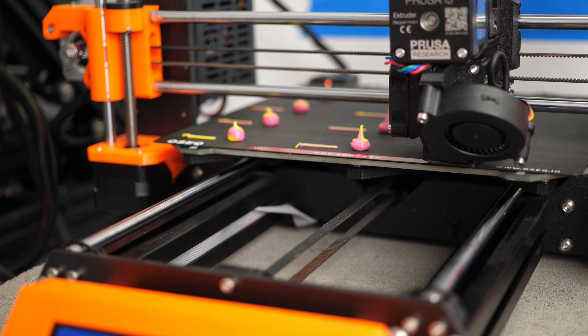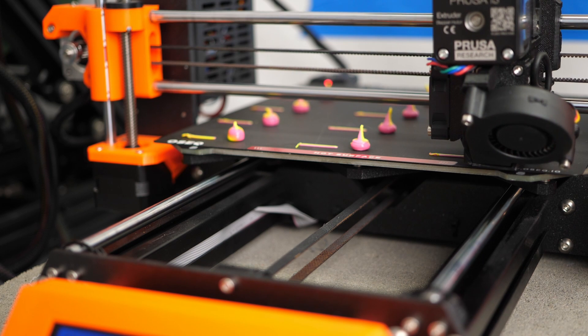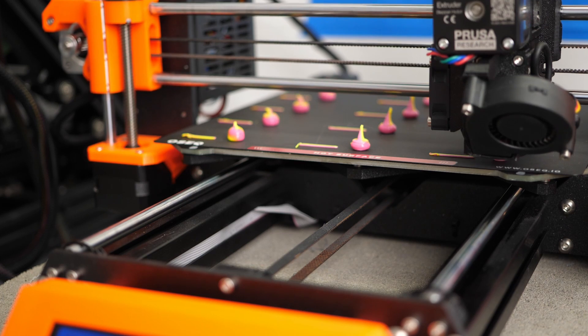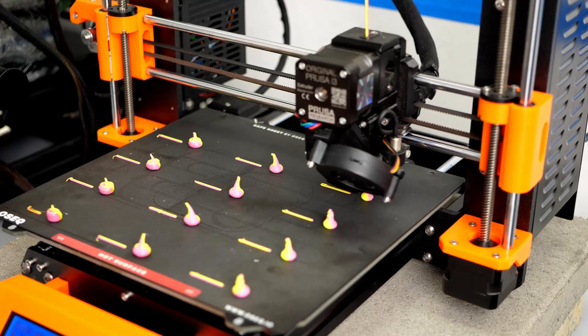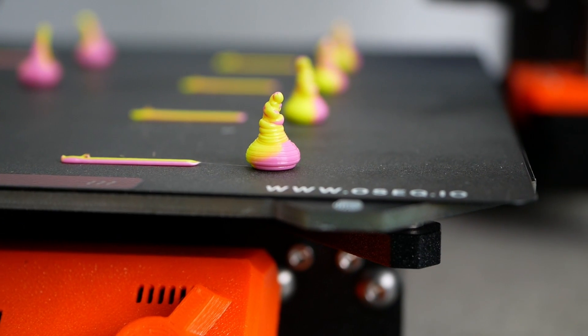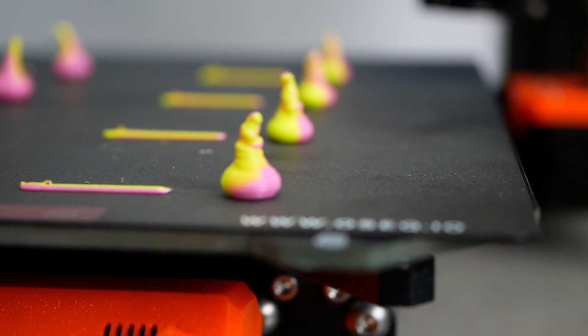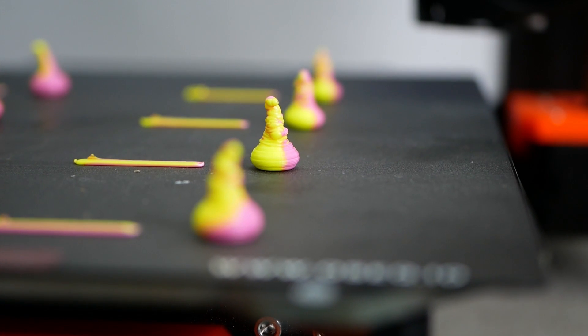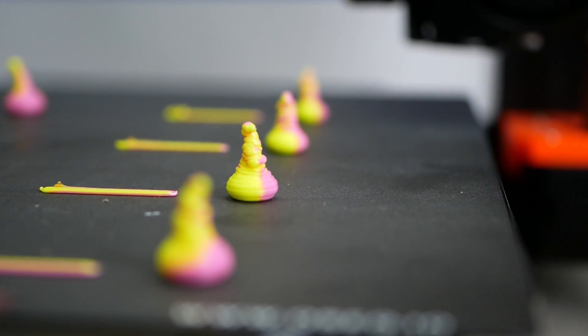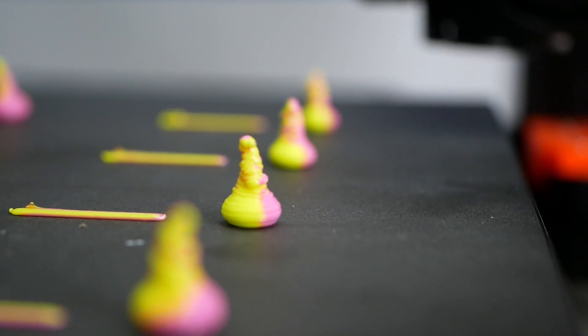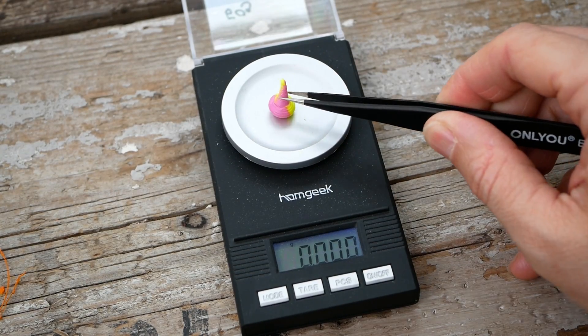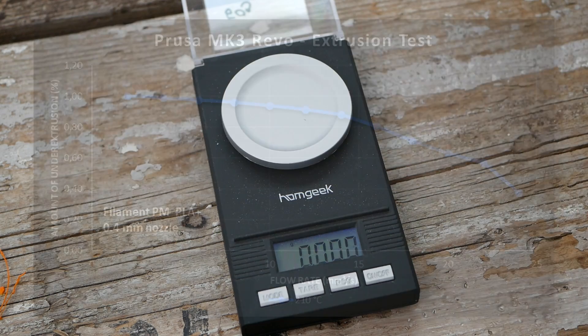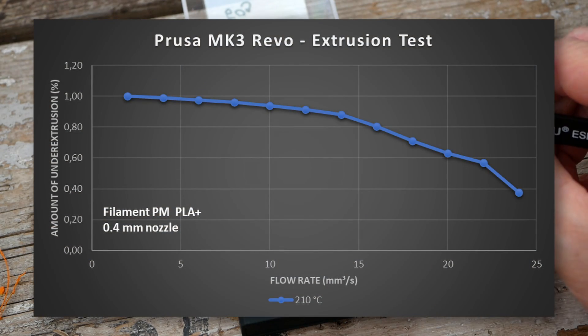Here the printer first purges the already preheated material quickly out of the nozzle and then extrudes a blob of material at different flow rates until the print platform is full. Each of the blobs should be made from 200mm of filament, but the faster we feed the filament, the more it slips and the less plastic will be extruded. When the test is over, I weigh each of the blobs on a milligram scale, which you can get for cheap on Amazon, and plot the weights over the feed rate.